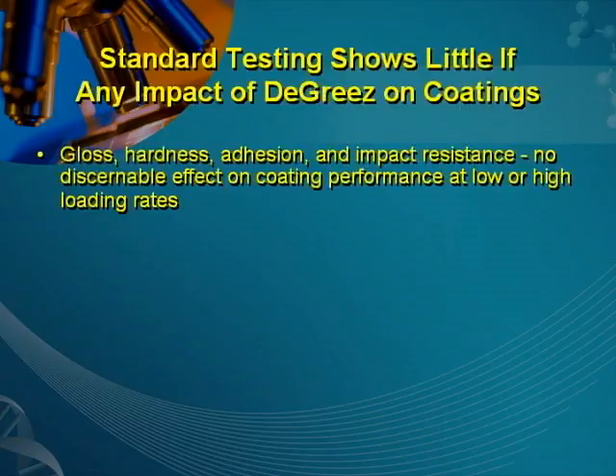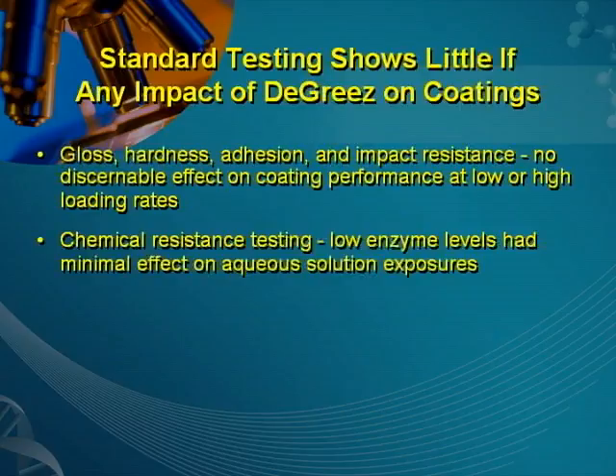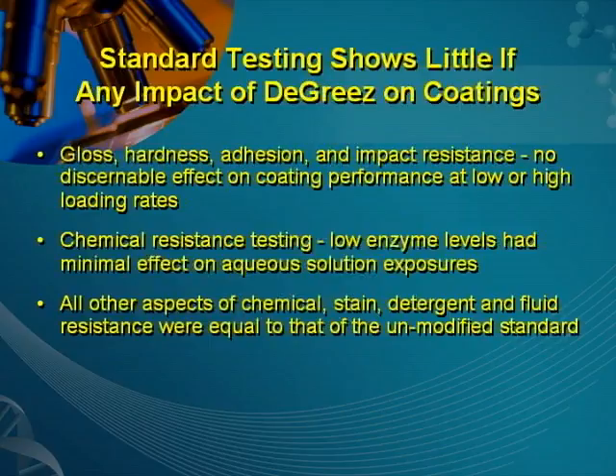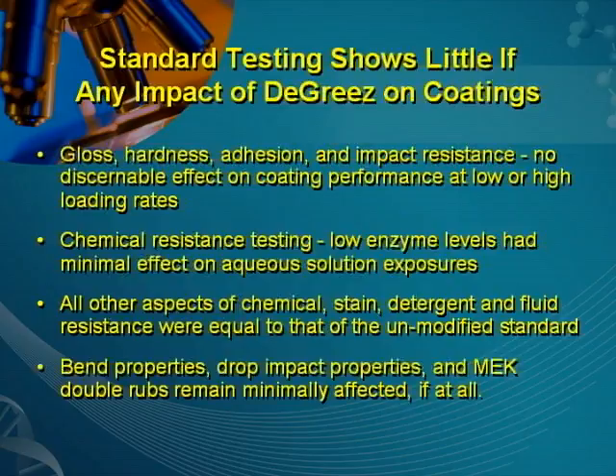Gloss, hardness, adhesion, and impact resistance show no discernible difference when compared to the controls. Chemical resistance remains comparable, as well as do stain, fluid, and detergent resistance. The same is true of bend, drop impact, and solvent resistance. The new owner of the DeGreez product line can be confident that the additive will have minimal impact on coating specifications for a large array of coatings.